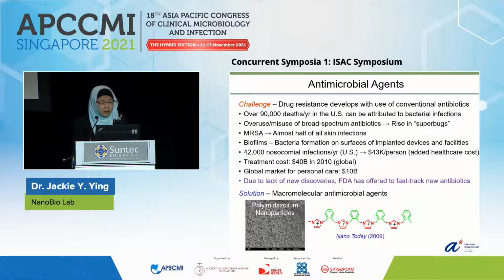For example, these polyimidazolium nanoparticles. In the backbone of this material is this imidazolium units, which provide us with a positive charge. And this will help us latch on to the negatively charged cell membrane of the bacteria and fungus. And then you can pierce through the cell and then cause the content to leak out and killing the cell without allowing it to have a chance to develop drug resistance.